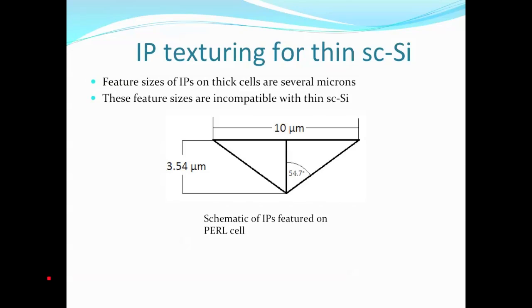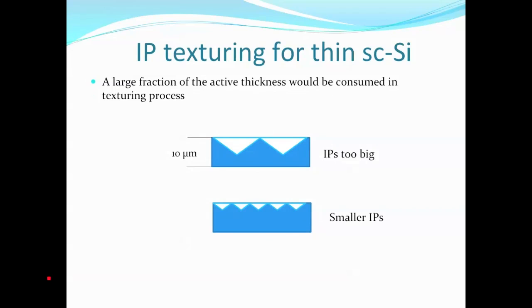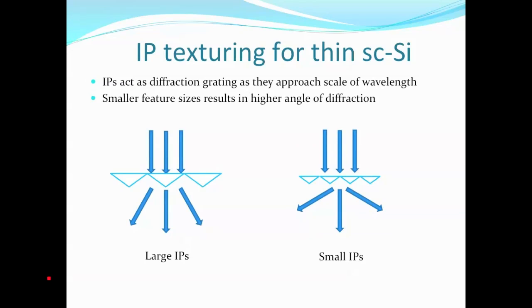The feature sizes of the inverted pyramids that are featured on thick silicon wafers are generally several microns large. These feature sizes would be incompatible with a 10 micron thick solar cell or less, because the active thickness of the silicon wafer would end up being mostly consumed in the texturing process. What we require are smaller inverted pyramids. Furthermore, when you push the feature sizes of these inverted pyramids down to the wavelength of light, they act as diffraction gratings. The smaller feature sizes you have, the higher the angle of diffraction. The higher the angle of light traveling through the cell, the longer its path length will be. It'll be absorbed more readily.